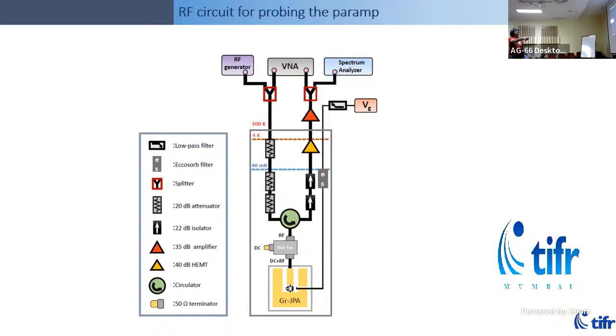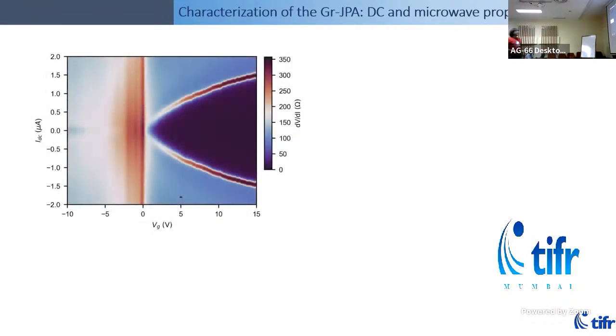This is the HEMT amplifier at 4 Kelvin, a room temperature amplifier, and then either a network analyzer or a spectrum analyzer. So this is the DC response of the device. This is the DC current measured as a function of the gate voltage, and this is the Dirac point, which is the point at which graphene has very few carriers, and the critical current, the supercurrent going through the device, becomes very small.